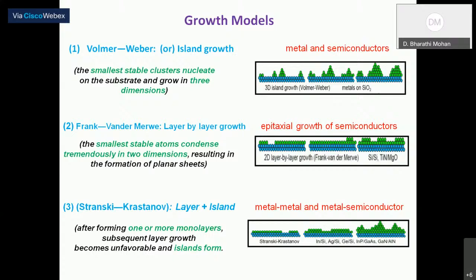It is nothing but the smallest stable clusters condense tremendously in two dimensions, resulting in the formation of planar sheets. So if you are growing silicon or titanium nitride on a substrate like silicon or MgO, then you form a layer instead of islands. The third model is the Stranski-Krastanov model, which is a combination of layer and islands. In this model, after forming one or more monolayers, the subsequent layer growth becomes unfavorable and forms islands. For example, if you deposit indium on a silicon substrate, it forms layers as well as islands.